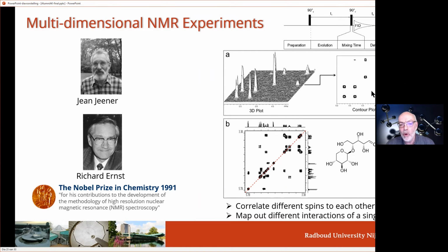Well, we hardly ever look at such plots. We plot so-called contour plots. And this allows us to correlate different spins to each other. So spins that are, for instance, bound because they experience a J coupling. But also you can map out different interactions of a single spin. For instance, see what is the chemical shift versus the dipolar interaction, or the chemical shift versus the quadrupolar interaction, etc. And this really has made NMR the extremely powerful analytical technique it is these days.